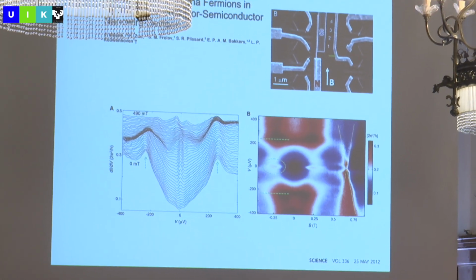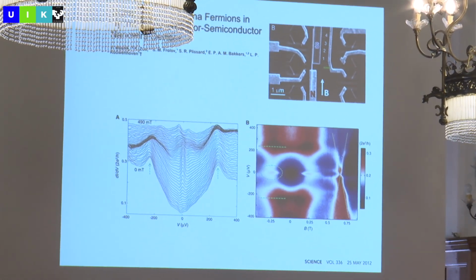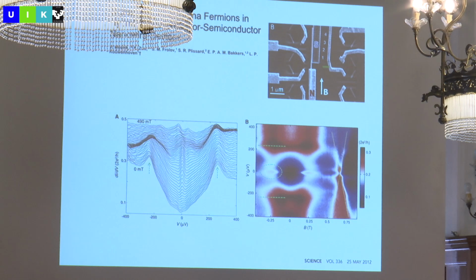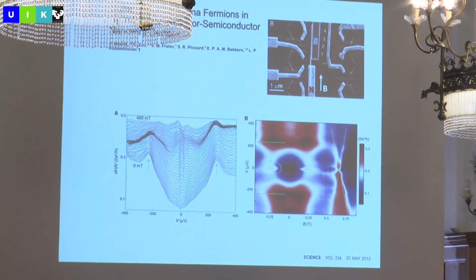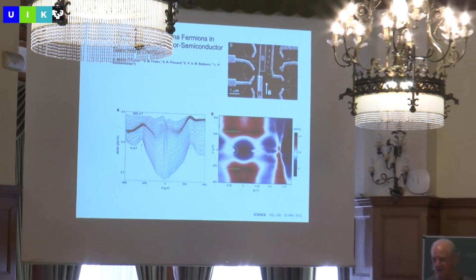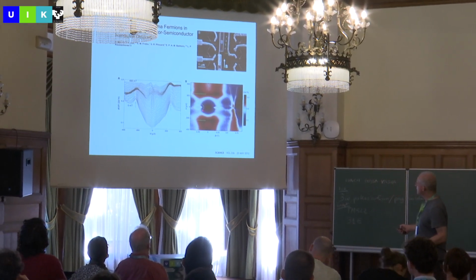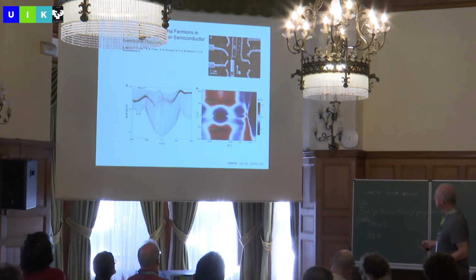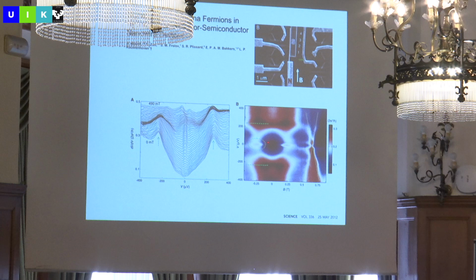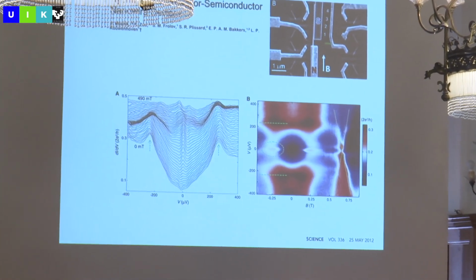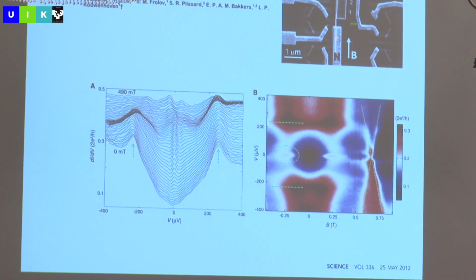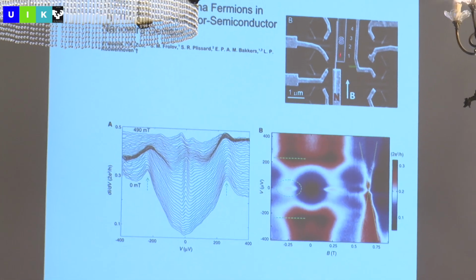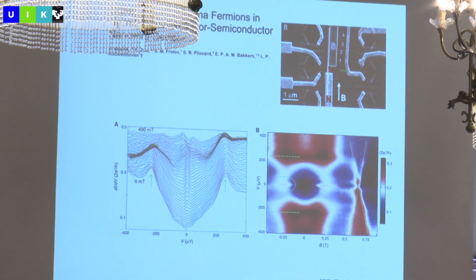And it didn't take that long between when the ideas and the numbers were plugged in, and here's what you ought to measure and here's what it ought to look like, before the Delft group published this paper, in which the remarkable observation being that at zero external magnetic field, indeed at low energy, lower than the gap, it was very hard to tunnel into a nanowire that was coupled to a superconductor, injected via a tunnel barrier into the end of a wire.